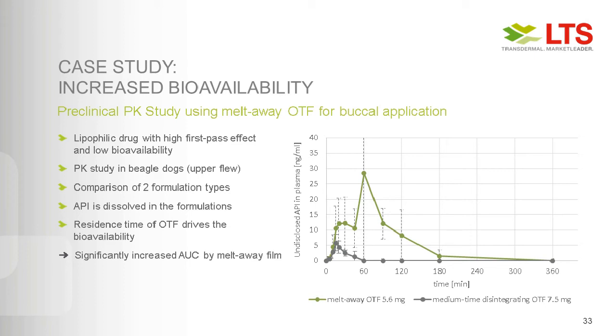And by moving into the melt-away film, which is here the green curve, which has a slightly lower loading due to the formulation type to still have it dissolved in the formulation, we could significantly increase the AUC, which was the key driver here within this project, which was needed compared to the oral dosage form.